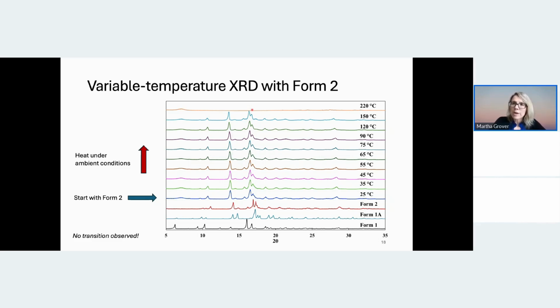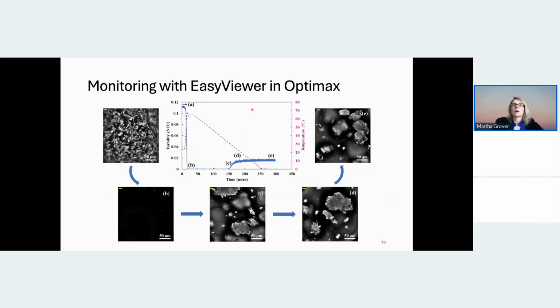And so we then also wanted to have slightly larger volume crystallization. We wanted to create more material and also to see about the scale and if there was a dependence on the scale. So here we crystallized in Mettler-Toledo Optimax 250 milliliters and observed with various PAT. Originally we heated up, dissolved the material, and then we cooled down. And then we have an Easy Viewer and can calculate the turbidity from that.